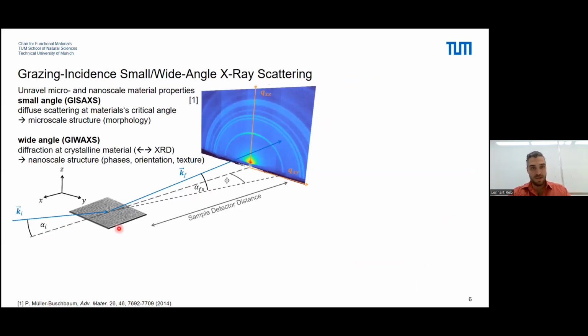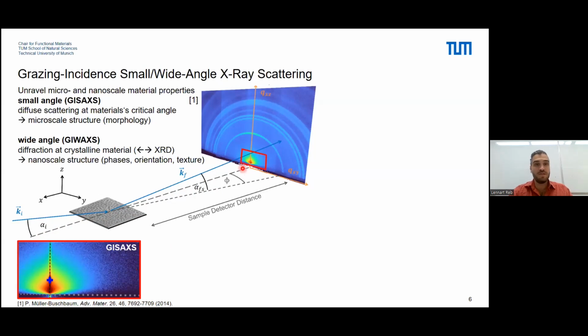scattering. So here you can see the classical setup. We have an X-ray beam that is coming in at a shallow angle onto a sample, and the scattered intensity is detected with a two-dimensional detector. So we have the small angle scattering. That means we're looking at intensity that is scattered in the small angle, that is GISAXS. So basically, this intensity arises from diffuse scattering at the material's critical angle. And by doing that, we can get information about typical sizes inside our thin films, ranging from a few to hundreds of nanometers. And this is what I call here microscale structure or morphology.